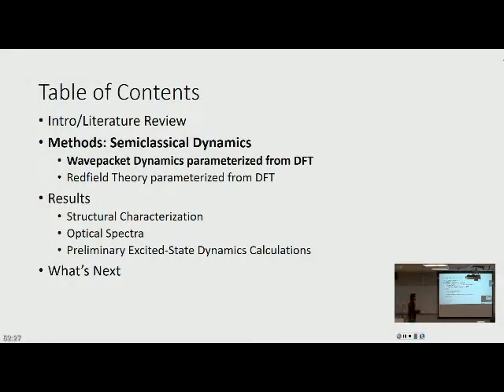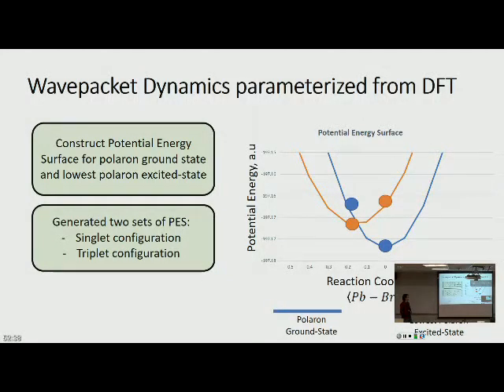And so, yeah, just an overview of a couple of ways we're going to try to quantify polaron emission in these systems. This was the project we had some initial results for Ben, who was in Dimitri's PChem class. So over there you might have seen some of these results, but basically we want to do wavepacket dynamics for the polaron ground state, and then the first, or the lowest, polaron excited state. And then we parameterize it with DFT. So these potential energy curves come from DFT calculations, where first we do a polaron ground state geometry optimization, which is this point. And then we just do the lowest excitation in DFT, and then optimize that structure.